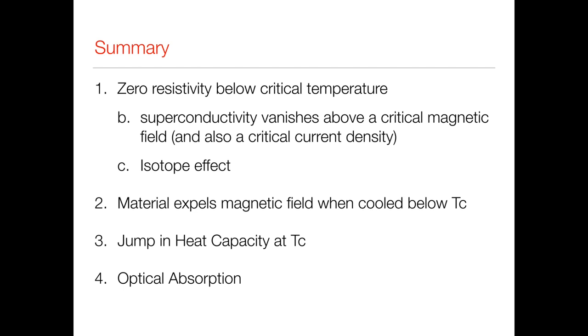We knew experimentally that there was a jump in the heat capacity at the transition temperature. We always expect jumps in heat capacity to be related to an excitation effect, and indeed here the excitation effect is the breaking apart of Cooper pairs. Okay, if we give enough energy, we can break apart a Cooper pair. And finally, we knew experimentally that, for example, optical absorption, so in the light regime, was the same between a superconductor and a metal. But in the microwave regime, there could be a sort of threshold in which we'd go from absorption to no absorption. And we understand that in terms of a gap, where the gap is in the millikelvin regime. So that's directly in the microwave region.